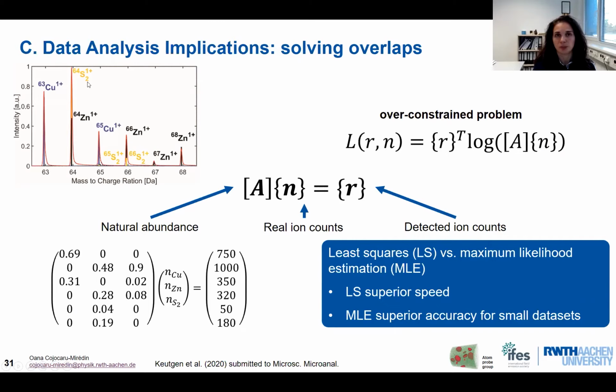on the mass spectrum. And of course, correcting a mass spectrum is an over-constrained problem. So the problem is that we have more equations than unknowns. And we have this formula in the center. Here we have the natural abundances, here we have the real ion counts, and here we have the detected ion counts.